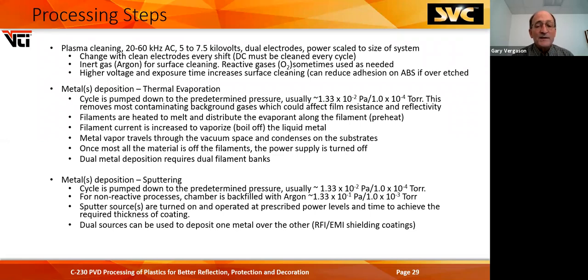In thermal evaporation, the chambers pump down to pressure, usually 1.3 times 10 to the minus 2 Pascal, or 1 times 10 to the minus 4 torr, to get rid of most of the water vapor in there. Filaments are heated to melt and distribute the evaporant. And then it's ramped up, boiled off, and condenses on your parts. That's a very fast process. In many cases, you're talking 30 seconds of coating time to do all those parts. Once all the material is off the filaments, power supplies are turned off. If you don't turn the filaments off, you're going to burn your parts.